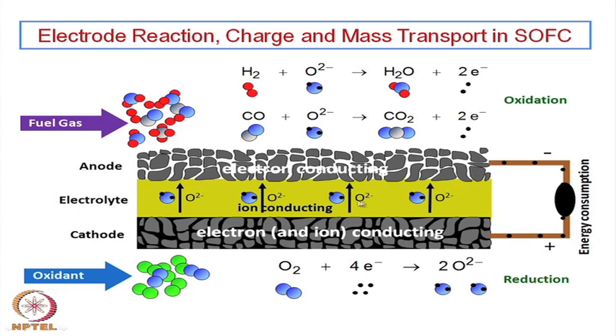So, this electrolyte has to be completely dense, so that molecular oxygen diffusion is avoided. Oxygen molecules should not pass through and then combine with hydrogen. If that happens, then it is only a thermal combustion, it is not an electrochemical combustion. So, electrical energy cannot be generated by that process. So, there should not be any porosity or continuity of the pores. Even if some small pore is there, it has to be discontinuous or an entrapped pore. This is one of the major requirements so far as the solid oxide fuel cell is concerned.